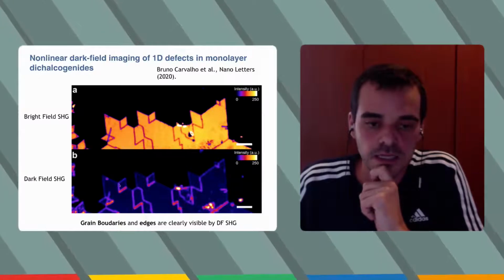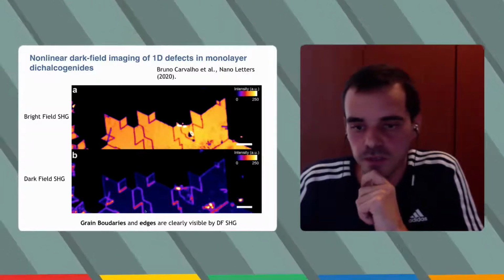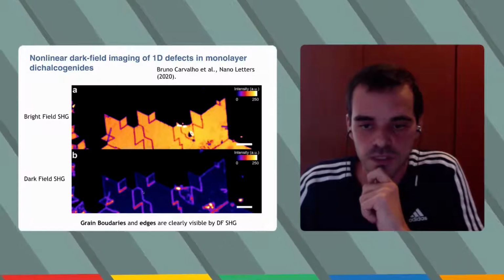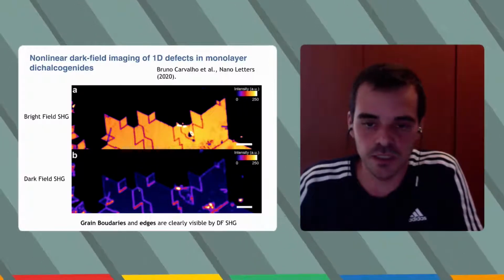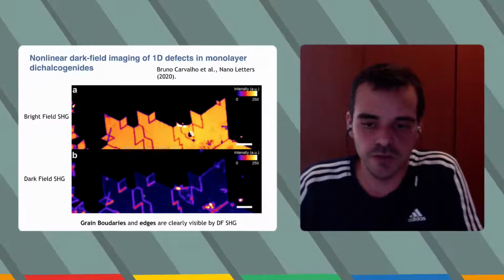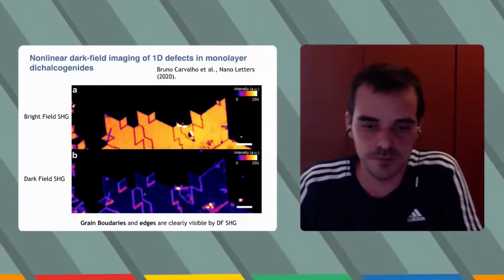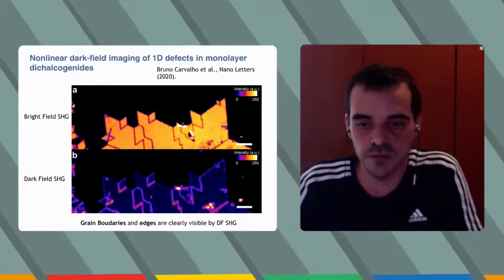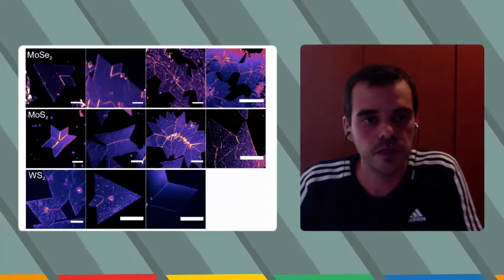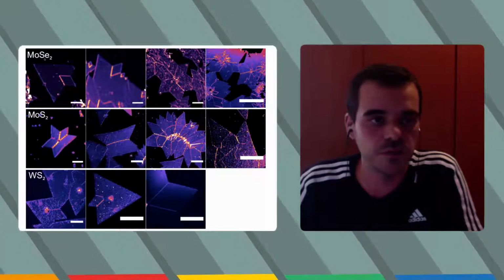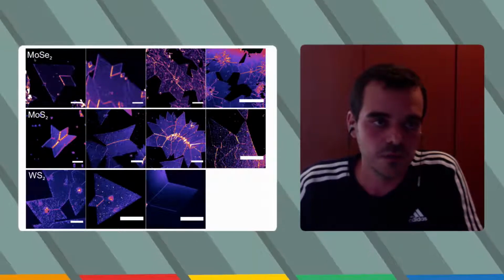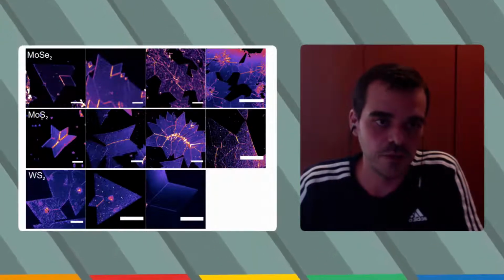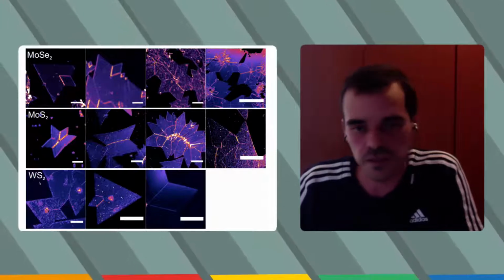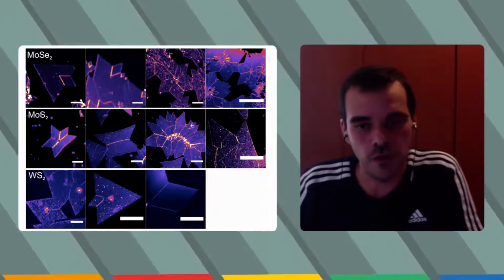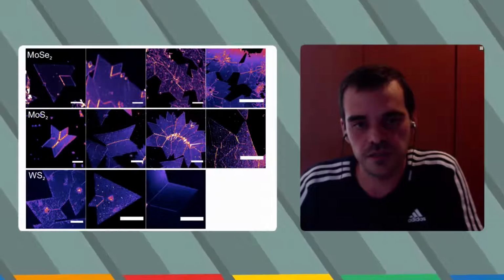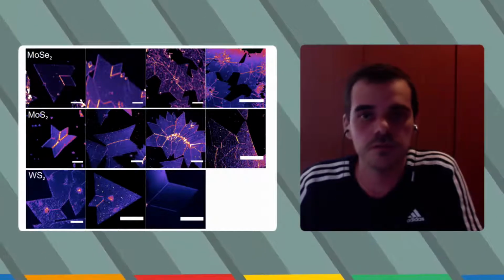Then we can reveal where the grain boundaries are. So by doing this type of measurement, we reveal the type of defects that we have and the amount of defects. You can see the edges and the grain boundaries of the crystal. These are different examples for different 2D materials: molybdenum diselenide, molybdenum disulfide, and tungsten disulfide. With all of them, we can locate the defects and all the grain boundaries in the crystals.